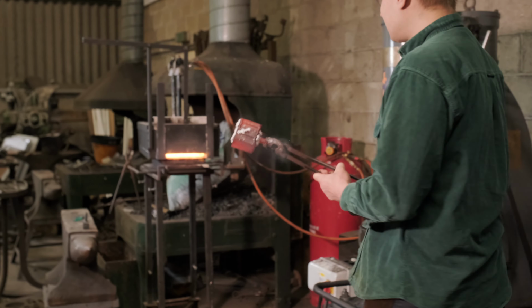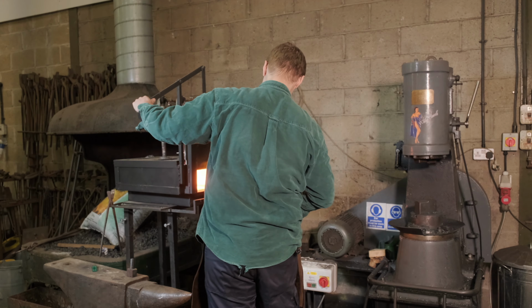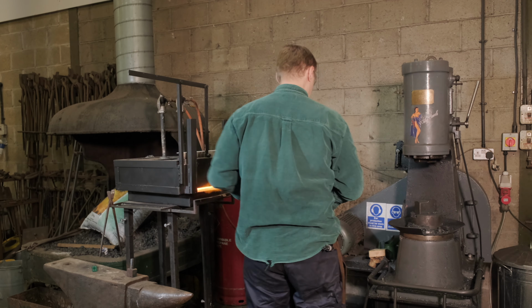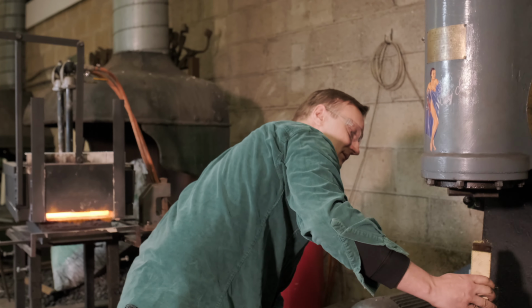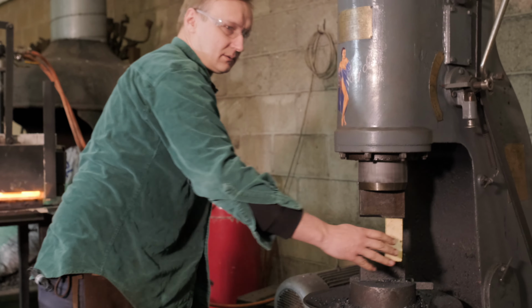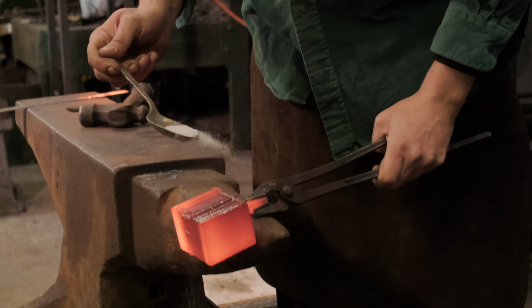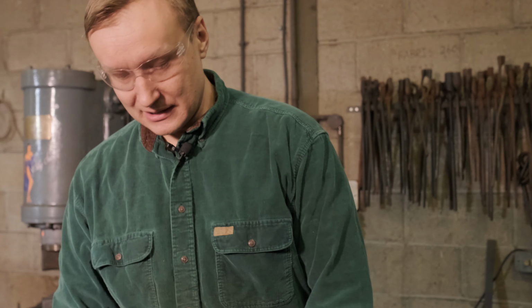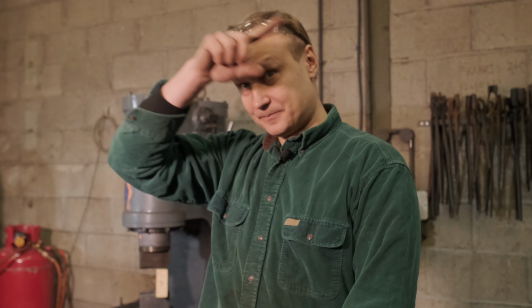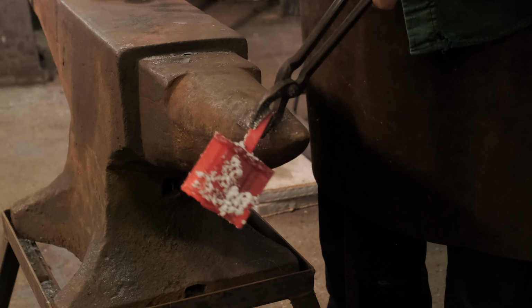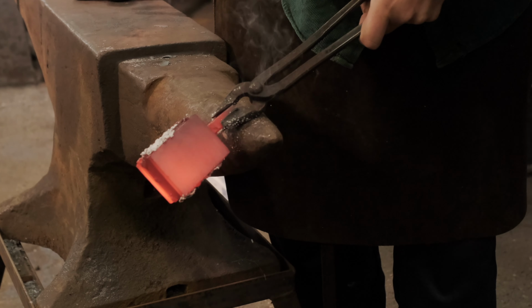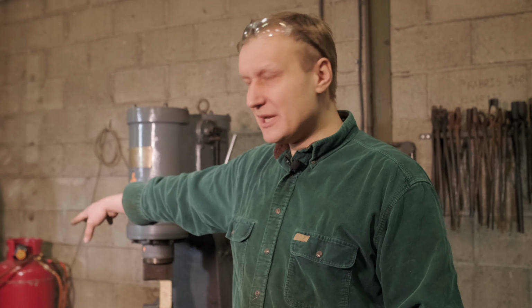And what borax does, it actually doesn't help with the forge welding itself. It creates a layer around your stack and will prevent the oxygen from getting closer to the steel. So that should prevent any oxidization in between the layers of the stack if we end up with any gaps. There shouldn't be any gaps.